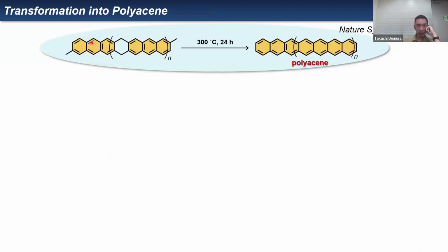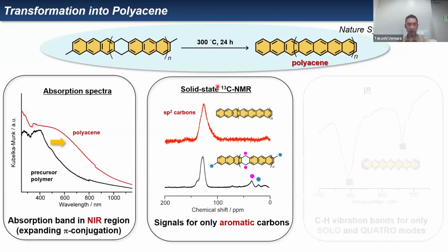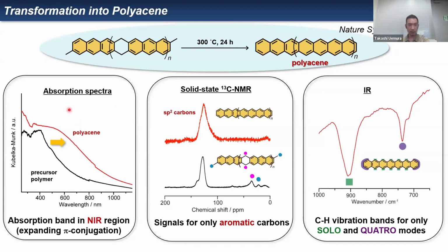Then next we performed the transformation of this precursor polymer into polyacene just by heating. Then we checked the absorption spectroscopy. We found the absorption band in the near IR region, showing the expansion of the pi-conjugated system. And the NMR showed signals for only aromatic carbons. And IR showed the CH vibration bands for only solo, the repeating groups, and quattro, the terminal groups, characteristic of the extended acene.